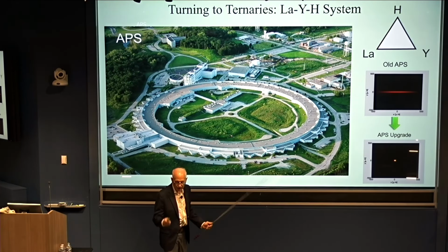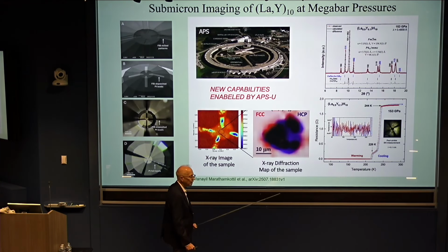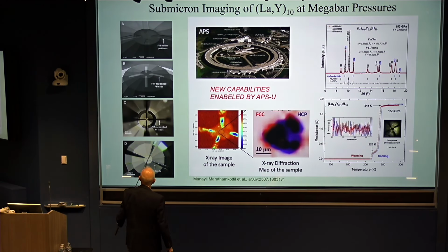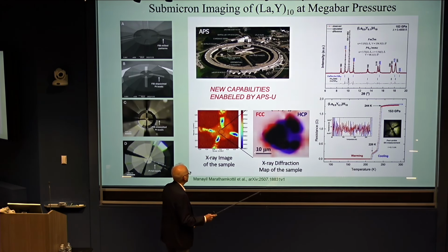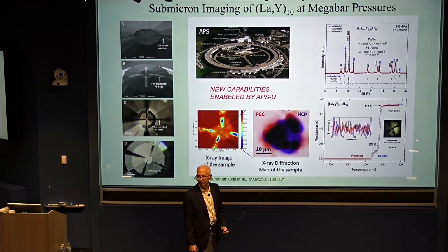So we can use this X-ray microscope to probe in great detail these phases that we make, because some of them have inhomogeneities and differences that we need to explore. So if we combine that with various ways we're putting electrical leads on our diamonds for electrical measurements, and then we take this to the Advanced Photon Source, which is just 30 minutes away from my lab, and we use these micron-sized beams, we can map out in great detail the sample. So this is a sample sitting at something like 1.5 to 1.8 million atmospheres pressure. We're sending the X-rays through. At the same time, we can measure the electrical resistance. We can map out where the leads are.